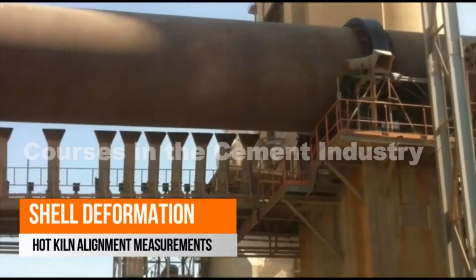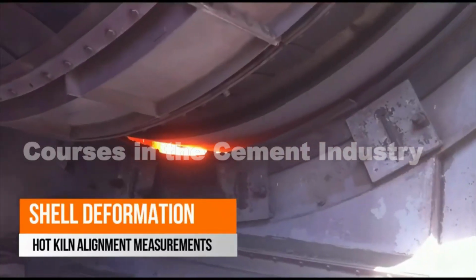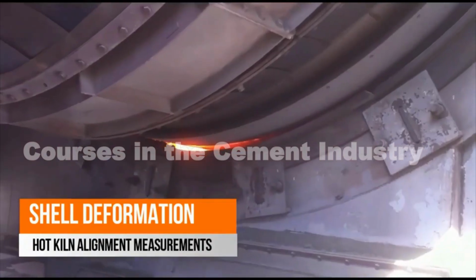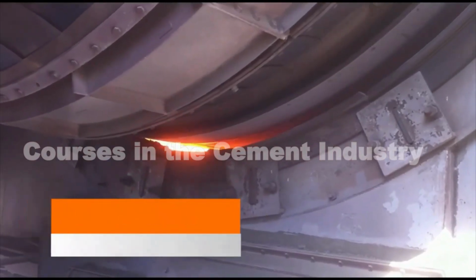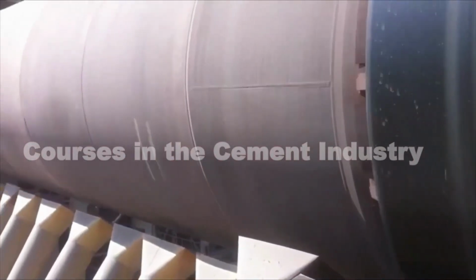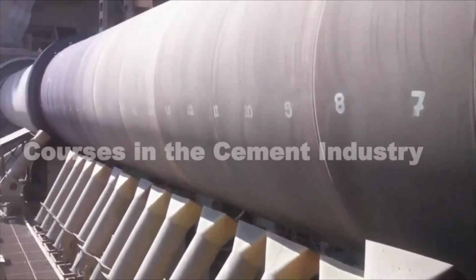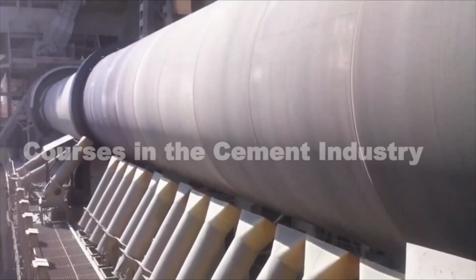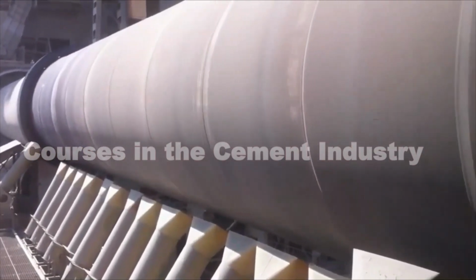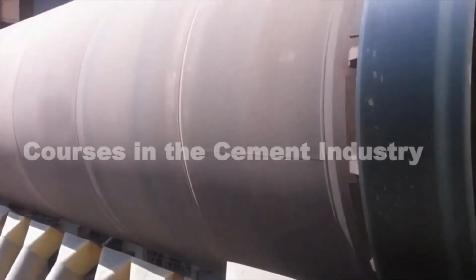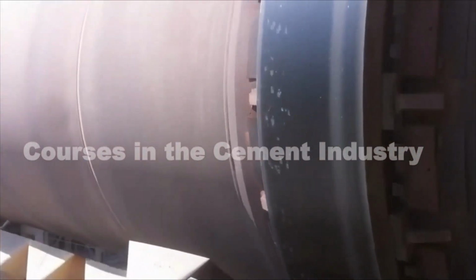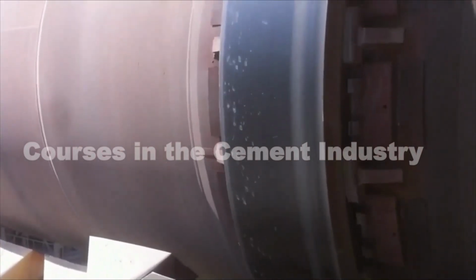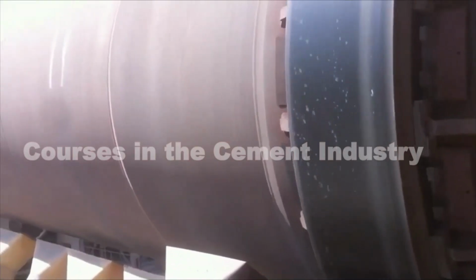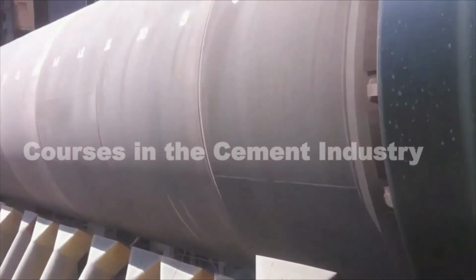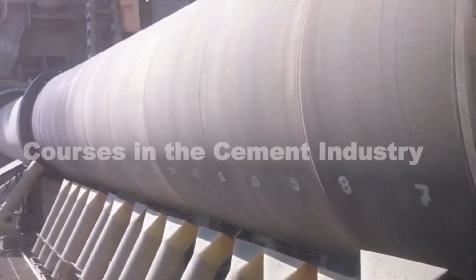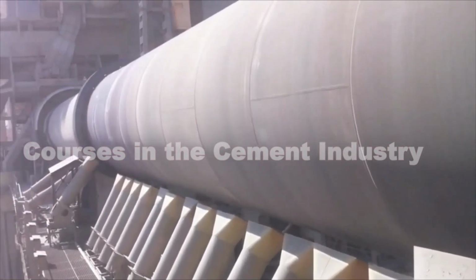The shell of rotary kilns operates at high temperatures. In case of excessive heat, the shell might deform or deflect. High values of local deformations can cause problems with the kiln's internal refractory lining, which has a negative impact on its lifetime. Moreover, any type of alignment deviation in the shell transfers very high forces to other kiln components, causing their gradual and faster wear.